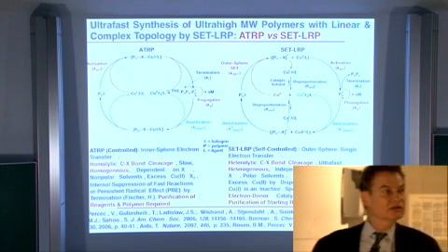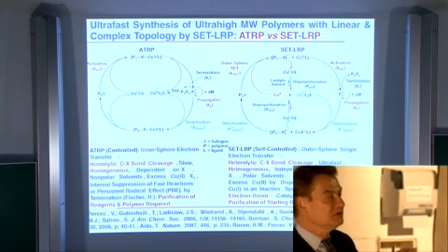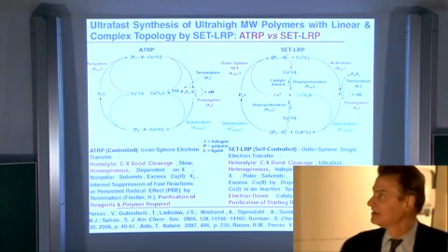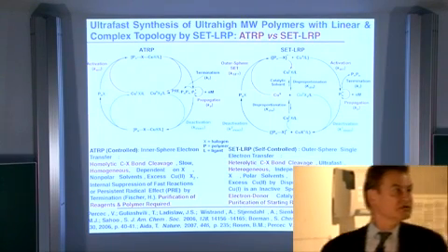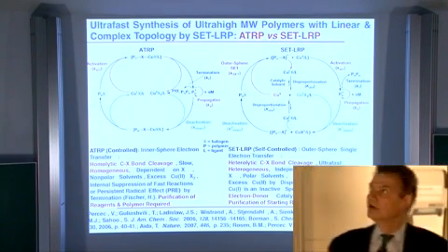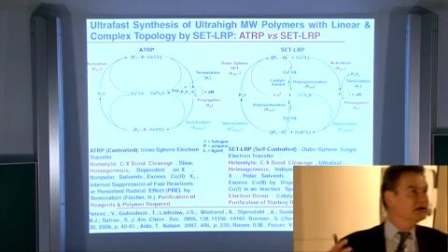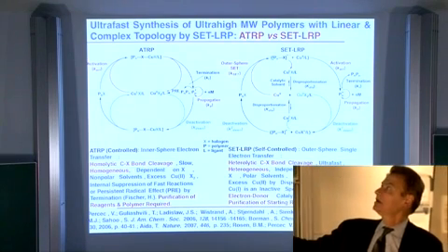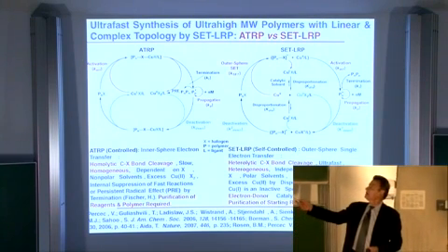So we change this reaction very little, into a reaction mechanism that resembles somehow the difference between SN1 and SN2. You get the same product, but the mechanistic pathway differs relatively substantially. Rather than using copper-1, we use copper-0. Copper-0 is a very good electron donor, and therefore transfers an electron to the alkyl halide, which becomes a radical anion. Whether it's a concerted or stepwise process is not important, but the halide leaves as a halide anion rather than by homolytic bond cleavage. And there is a problem now.